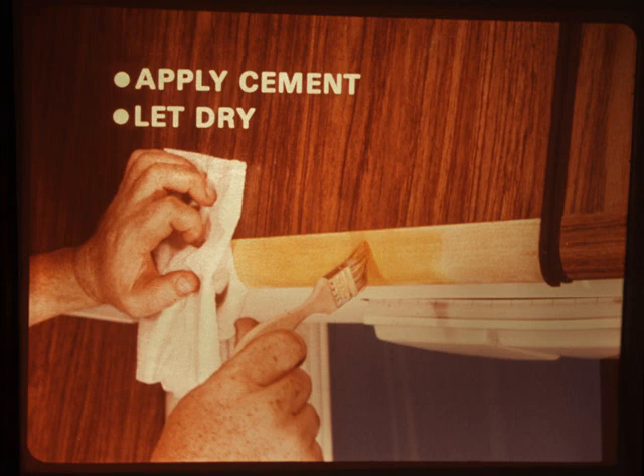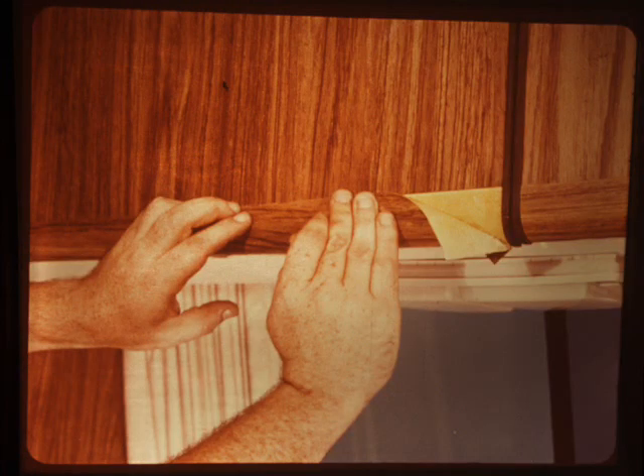You should use 3M's Scotch Grip number 2210 contact cement for complete delaminations, letting it dry for 20 to 30 minutes. For partial delaminations, you can use 3M's number 77 contact cement, which has to dry for only 5 minutes. After the cement sets, carefully place the vinyl in place and apply strong hand pressure across its entire surface. If there happens to be any cement overrun, just wipe it off with some solvent.